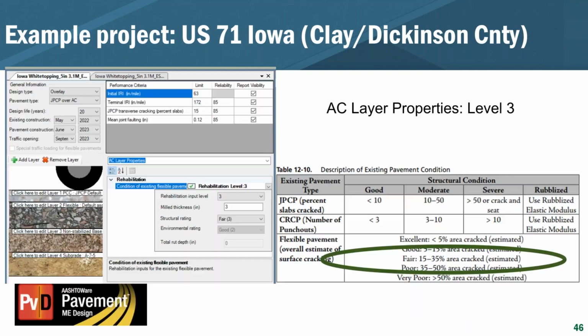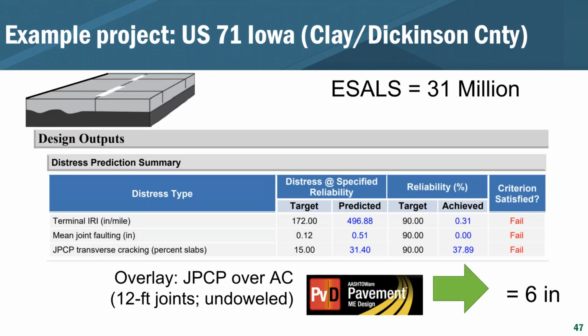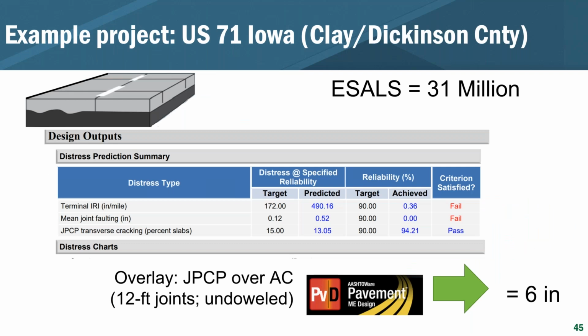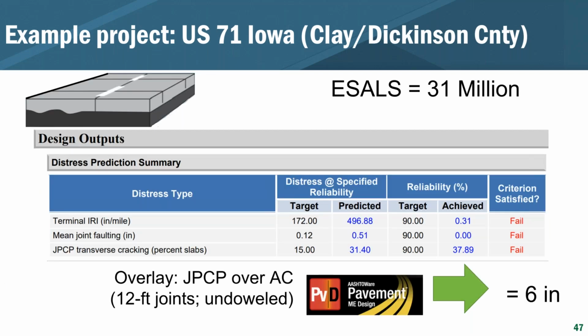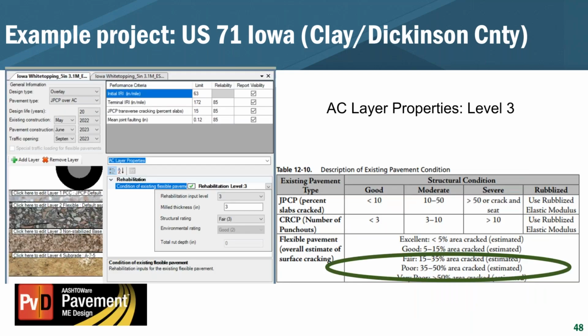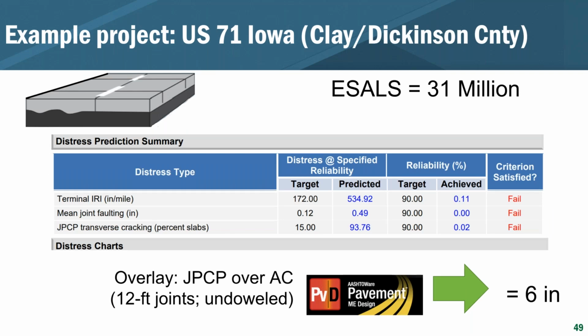What I want to do is look at how these different distress levels in the pavement prior to placing the overlay influence your overlay thickness. So again, before we were at good, but now I'm going to push that down to fair. So saying 15 to 35%, and then looking at the percent cracking. And I went, as you saw, from 13 to 31. So just by moving that down, it was pretty significant. And then going down a little bit more, you're going from 31 to 93. I didn't go down any further because, at that point, you're way outside the boundaries.